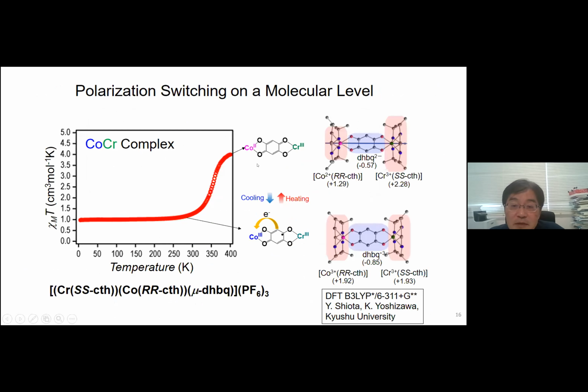And this is magnetic property. And as shown here, this complex exhibits electron transfer, Valence tautomerism from ligand to metal. Low temperature, cobalt 3, chromium 3. Heating, cobalt 2, chromium 3 because of electron transfer. And dipole moment is nearly 0. But this is dipole moment 9. So these molecules exhibit dipole moment switching between 0 and 9. This is molecular level switching.